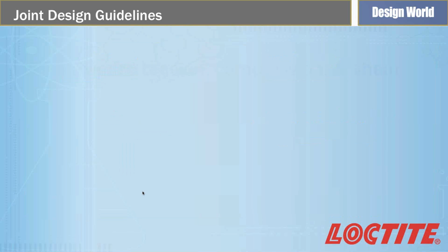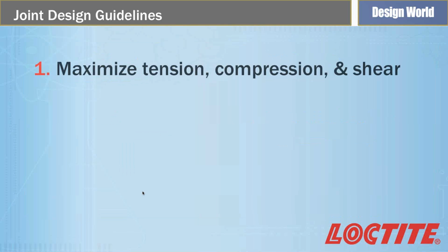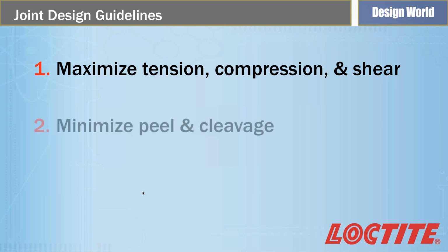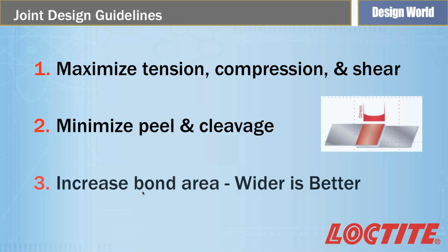So in summary, for joint design, you want to maximize tension, compression, and shear. Those are the ones that are going to give you the most ultimate strength out of your assembly. You want to minimize your peel and cleavage. That's focusing the stress on one point, and you're losing that benefit of the adhesive to be able to distribute the stress evenly. And lastly, you want to increase your bond area. And remember, wider is better. Any way you can increase the bond area is going to help, but if you know the direction your stress is going to come from, if you can make that leading edge wider, it's going to give you a stronger ultimate assembly than if you make it longer. So those are the three major joint design guidelines when working with adhesives.